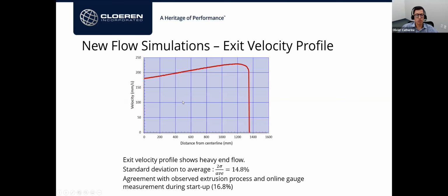So if I plot this velocity profile at the die exit, I can definitely see the combined effect of higher melt temperature and new viscosity behavior, and see that there is definitely a resulting push towards the edges. And the actual 2 sigma calculation for this profile is about 15%. It's not that far from what they observed at 17%. So I was quite excited to see a good match like that.